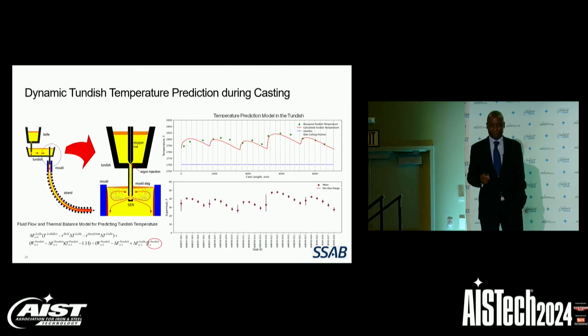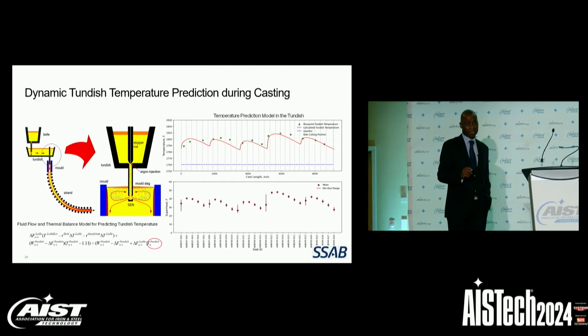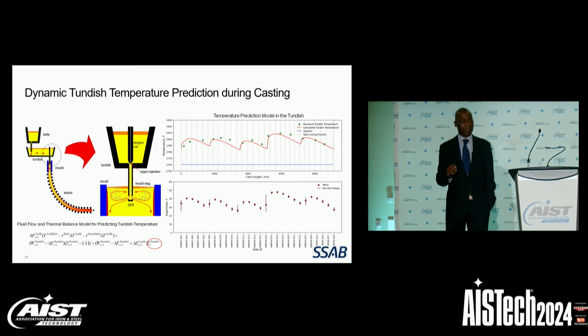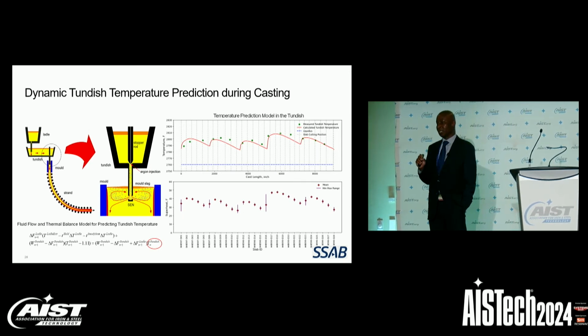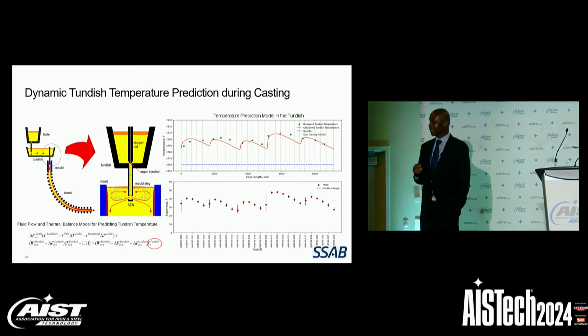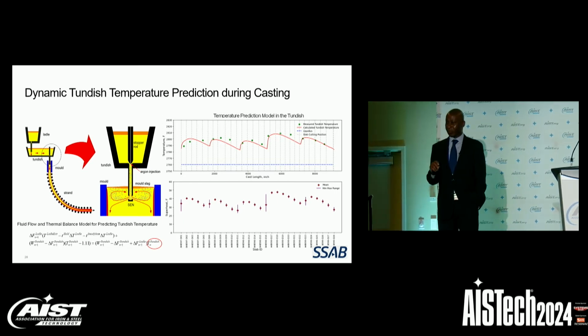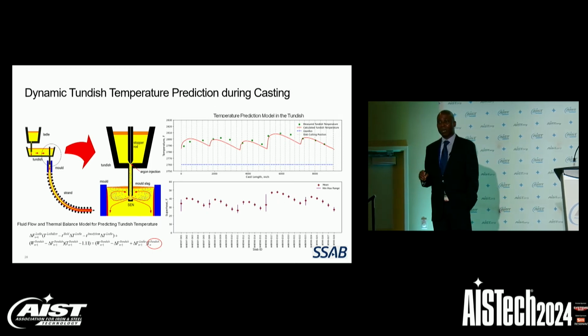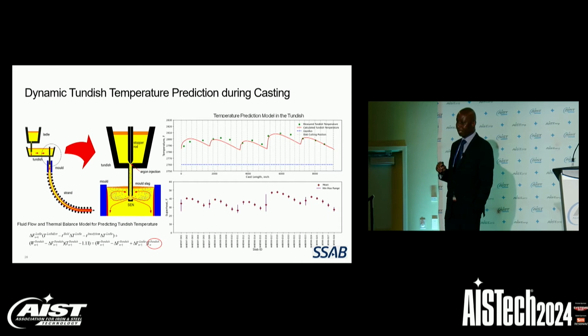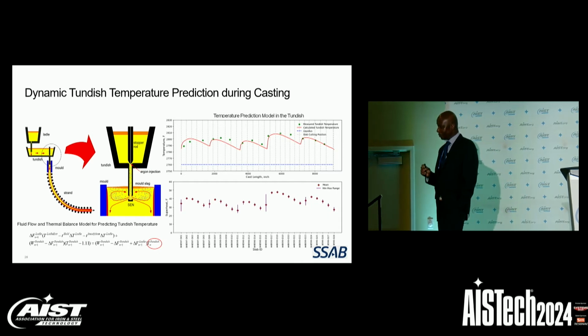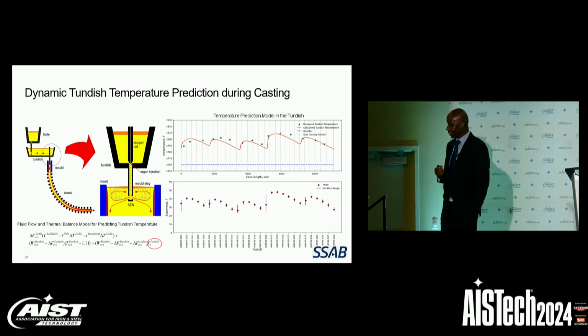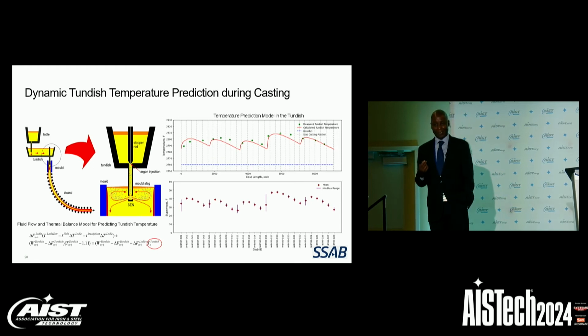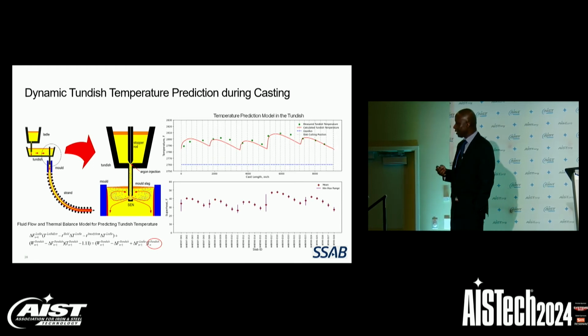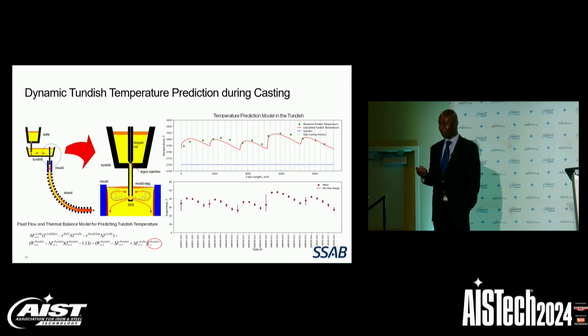So temperature of the liquid steel during casting is very important to the operational efficiency of casting and to the surface and internal quality of the as-cast product. Temperature is measured in the tundish either with a continuous temperature measurement sensor or intermittently with a temperature probe. Continuous temperature measurement sensor, you learned this already, is maintenance intensive and costly. Intermittent temperature measurement is not good for process optimization and control.